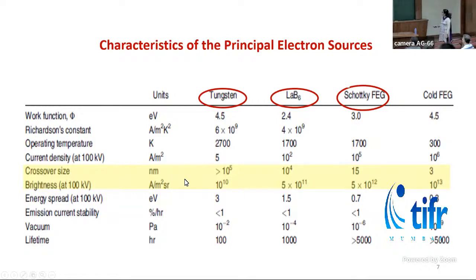Second thing to be noted is the brightness. The brightness decides the current in the beam. So here also we can see that tungsten has the brightness of the order of 10 to the power 10, and Schottky field emission gun have brightness of the order of 10 to the power 12. So this is very important when we are using microscope as an analytical tool. So by looking at this, we can say that field emission gun gives the best resolution. Our EVO LS10 SEM has tungsten filament. Tecnai 200 kV TEM has a LaB6 filament, and HR SEM and Titan, they have this Schottky field emission gun.